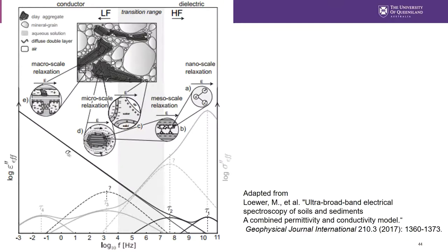When you apply an electric field, the molecules of water, which have a dipolar moment, will tend to align with the electric field. And this will create a specific relaxation due to heat loss between the molecules of water. Then if we go a little bit lower in the frequency range, we have this mesoscale relaxation. This relaxation is basically linked to the fact that the molecules of water, due to the bound water, will stick to the surface of clay grains. Because they are somewhat connected to the surface, they cannot move freely. So this is why the relaxation frequency is a bit lower.